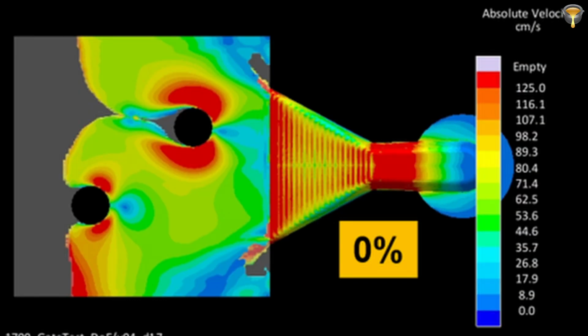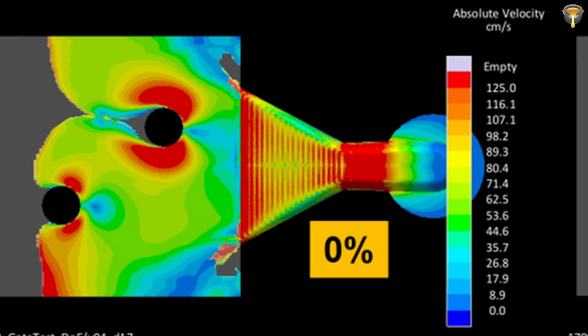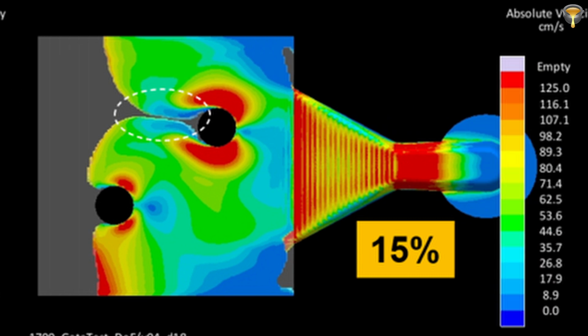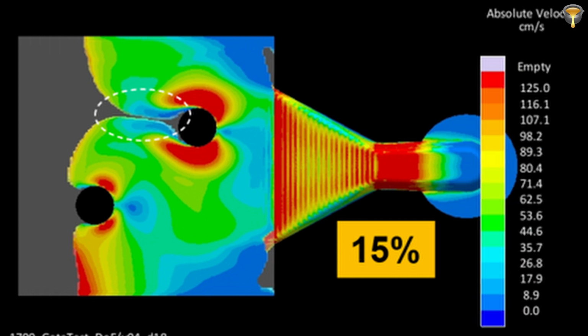And I have to break it to you, that is not true. Just because you have Rheocasting written on the package doesn't mean that you get a laminar fill. For the laminar fill, the solid fraction is key. So if you have 0% solid fraction, so you're casting conventionally, you always have that turbulent fill. And now let's add 15% of solid fraction. So 15% of the material is already pre-solidified when you use it. Yes, you see the first effects of semi-solid, but still the filling behavior is fully turbulent.